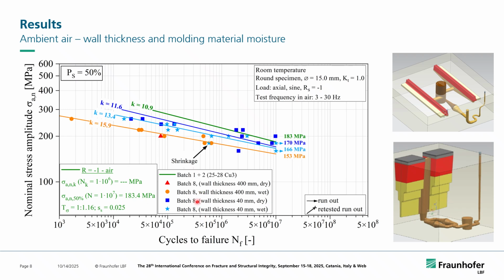At the end, what we see is that the wall thickness was a bit better for the 40 millimeter compared to the 400 millimeter, so this upper wall thickness here, but it could not catch up with the wall thickness here from batch 1 and 2, although the materials were comparable in the manufacturing process, had comparable chemical composition, and tensile parameters were comparable. So at this stage, I could not really figure out what the difference was, but that's the result that we saw, and we'll investigate this effect further.